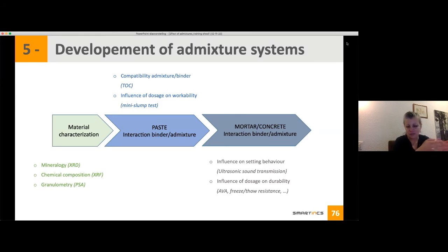AVA stands for air void analyzer. It's an equipment where you can see in your concrete, in a fresh state, how much air bubbles are there and how they are distributed. And this is really important when you work with air entraining agents, because you want to make sure that you have the right amount of the right size of air bubbles, with the right spacing factor. And this equipment can give you this information. And then you can also do freeze/thaw resistance.